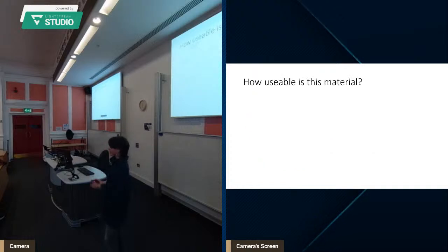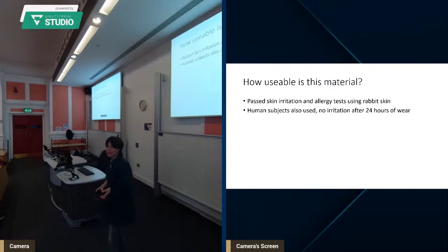So how usable is this material? How do we think the average customer will treat this product? So this product did successfully pass skin irritation and allergy tests. They used rabbit skin to experiment on this, but they also used human subjects. I want to point out that these human subjects wore these stickers for 24 hours. So this shows us the strong adhesion of this material, which I think is pretty beneficial for people who want to use this product long term.